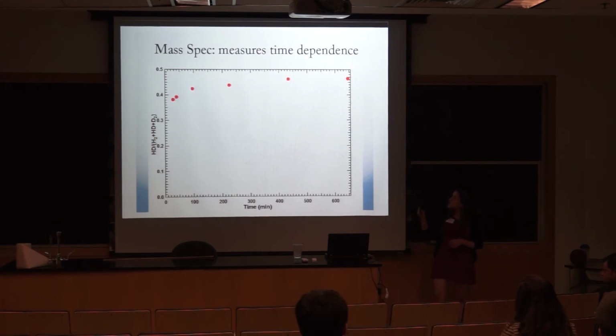It comes up pretty quickly to about 50%, which is good. It's what you'd expect statistically. We wanted to make sure that it wasn't just metal impurities, because metal surfaces can catalyze hydrogen on their own. So what we did is we exposed the sample to air, so water would go to all the metal sites, and we repeated it, and we got much less rate of HD formation.